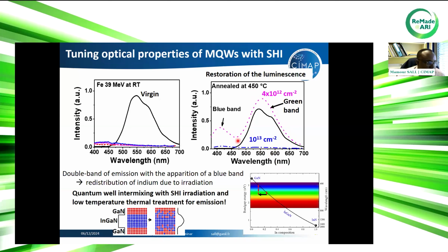This can be understood very easily when we look at this figure. It shows the evolution of the band gap as a function of indium content in indium gallium nitride. We go from an indium gallium nitride content that emits light in the green range. So if we have a blue band here, this means that we have shifted the indium content to the left-hand side. We are somewhere here, let's say, and this means that we have created a mixing, because if we decrease the indium content, we have created mixing somewhere at the interface. So by this swift ion irradiation and very low temperature annealing, we can create this quantum mixing we were looking for without losing the green luminescence.